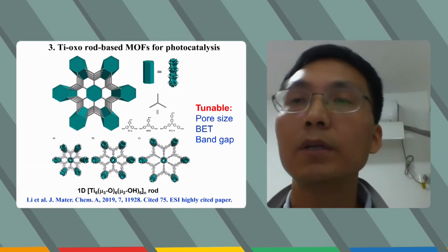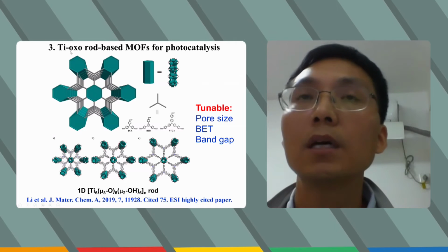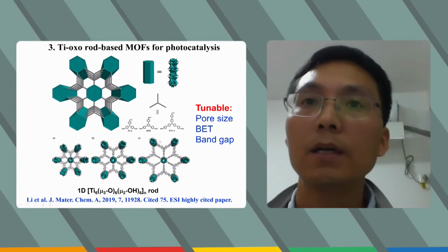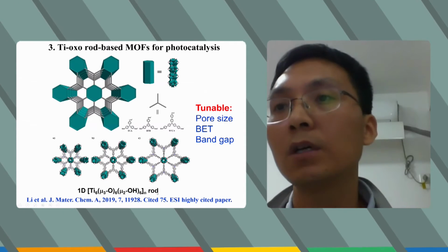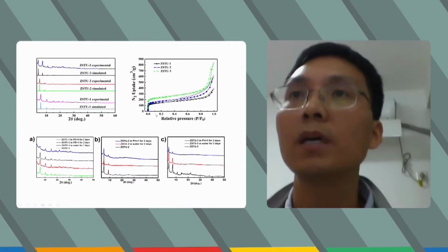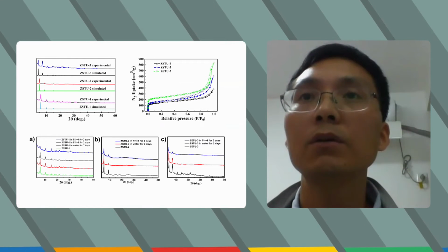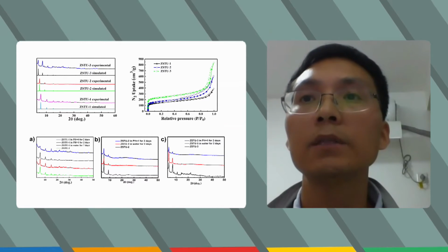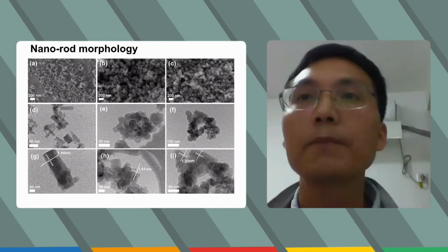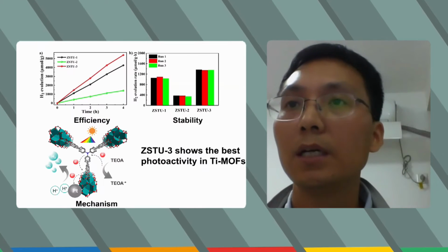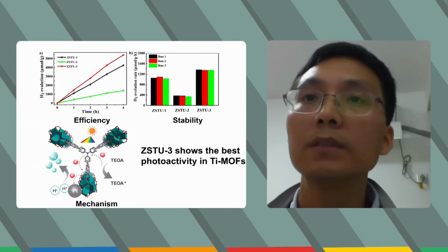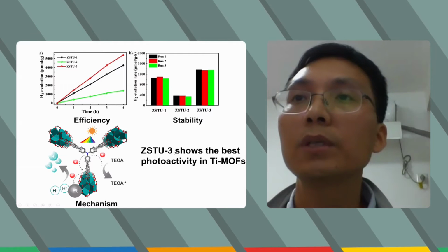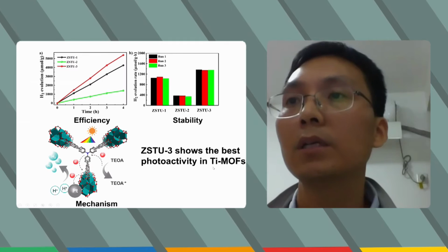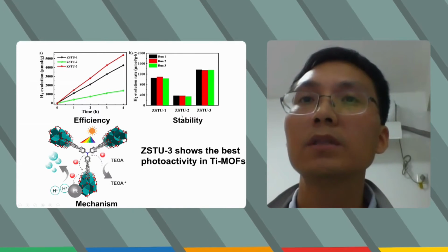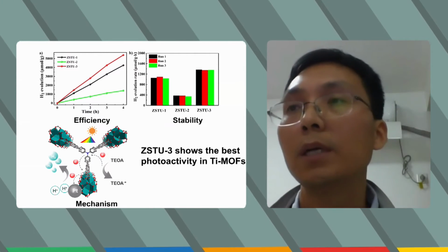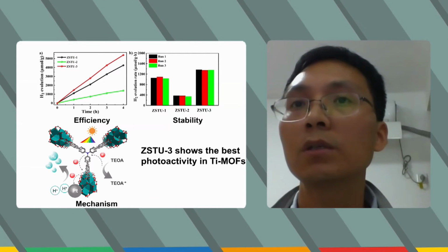Last is my recent work. We used three organic ligands to construct titanium oxide rod-based MOFs. These MOFs have a 1D titanium oxide rod. You can see that they have large surface areas, and they can be made at the nanoscale. They also have quite strong visible light response. These three MOFs can be used for hydrogen evolution. The last one, ZSTU-3, shows the best activity of all the MOFs, because it has a very large surface area and also a titanium oxide rod structure.